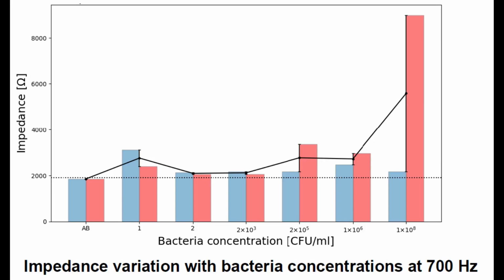Notably, there is no linear trend in impedance from 1 CFU per milliliter to 10^8 CFU per milliliter, suggesting the biosensor lacks an obvious sensitivity value. However, it is evident that the biosensor distinguishes between bacterial presence and absence, with blank sample pairs consistently remaining below others, thus establishing a detection limit at 1 CFU per milliliter.